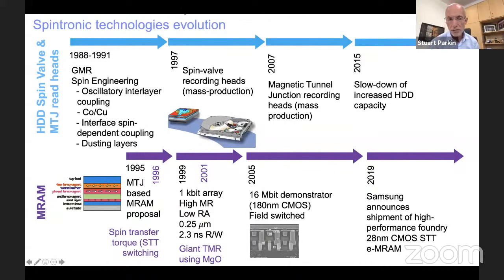In the case of using a spin valve and subsequently a magnetic tunneling junction as a device to sense magnetic fields within a magnetic disk drive, it took less than a decade from the discovery of giant magnetoresistance and my own work on discovering oscillatory interlayer coupling, giant magnetoresistance as a general phenomenon, and discovering that cobalt copper gives rise to large effects at room temperature, whereas the original discovery was made at very low temperatures in single crystal films and in very, very large magnetic fields. Then this only took a small number of years before it had an immediate impact. And within 3 years of its introduction, initially by IBM, it was used widely by the whole industry and could enable a very rapid increase in the storage capacity of magnetic disk drives by 10 times within 1 or 2 years. It had a dramatic impact.